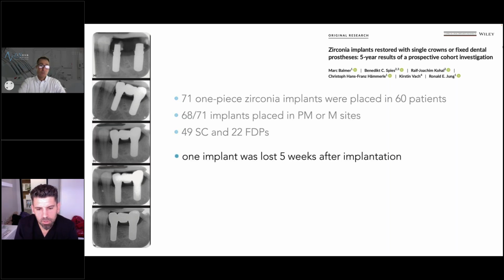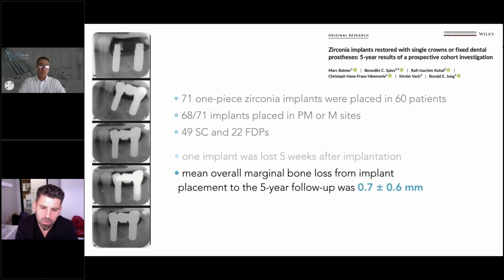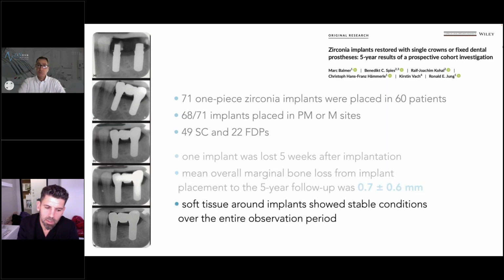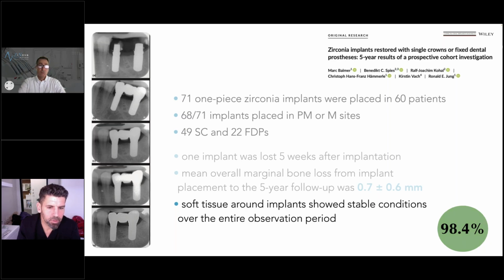Only one implant was lost after 5 weeks, so an early failure or loss of osseointegration. And at the end of the study, there was a mean overall marginal bone loss of about 0.7 millimeters with a 0.6 standard deviation. This is very, very good and very comparable to what we see in the titanium counterparts. Again, soft tissue around these implants showed very stable conditions over the entire observation period. And their success rate was 98.4%. So again, very high success rate, very comparable to what we see with titanium implants.